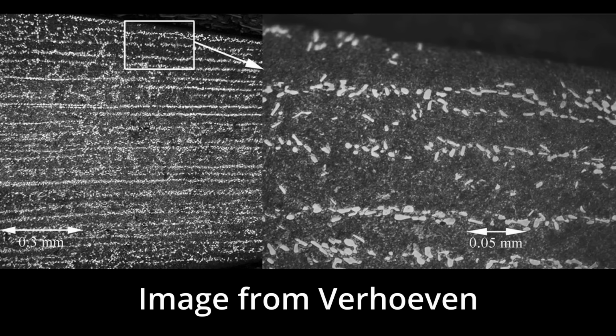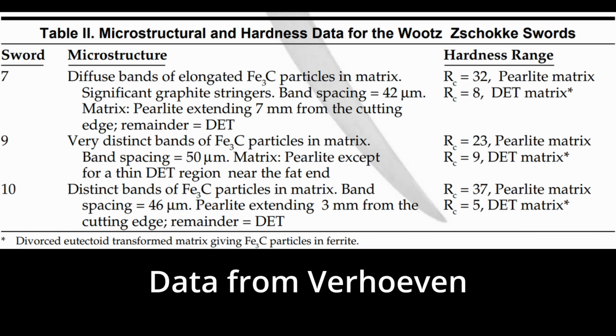The reason why both Pertula and Verhoeven tested Wootz steel at relatively low hardness, like 40 Rockwell, was because a lot of the ancient blades that have been tested had a pearlite microstructure. And that was in part because quench and tempering wasn't very common yet anciently, and also because the hardenability of the steel was so low. So even if they were quenching and tempering it, it may not have been achieving a martensitic microstructure. So edge retention and edge strength of ancient Wootz blades would likely have been relatively low because they often had low hardness, compared with modern Wootz steel that we can make, which can be cleaner, and we can control the carbon content better, and we can achieve 56 to 62 Rockwell like other modern knives.